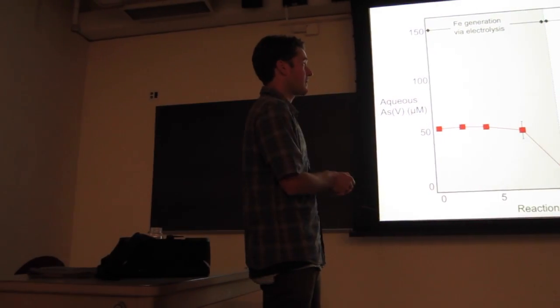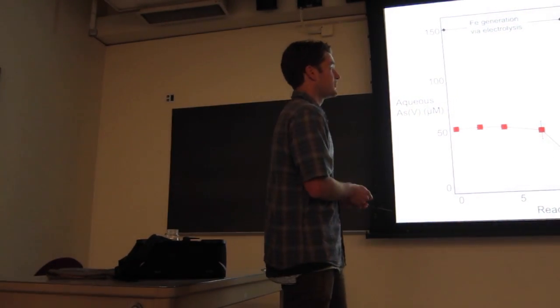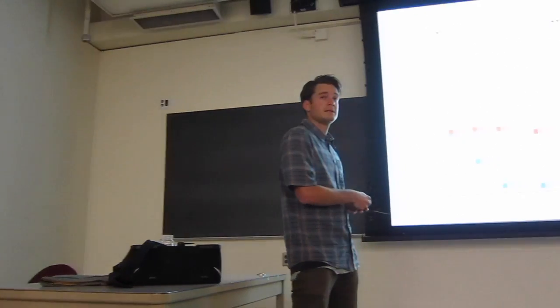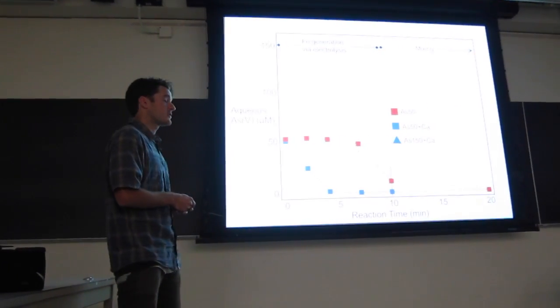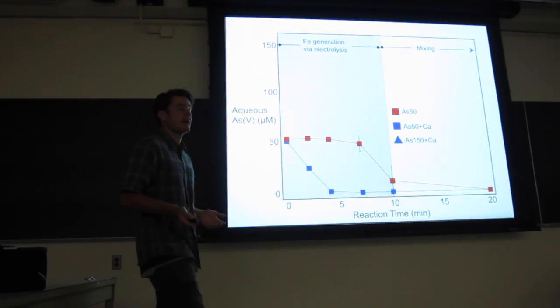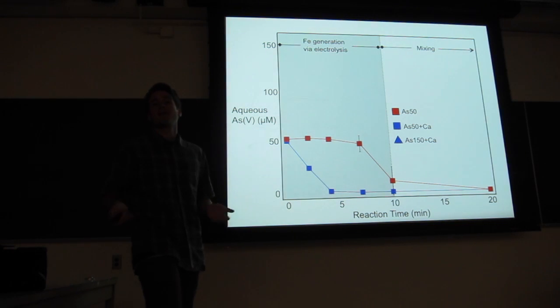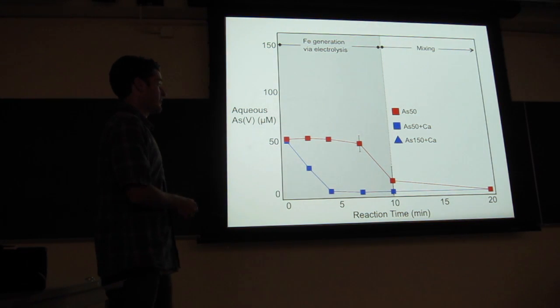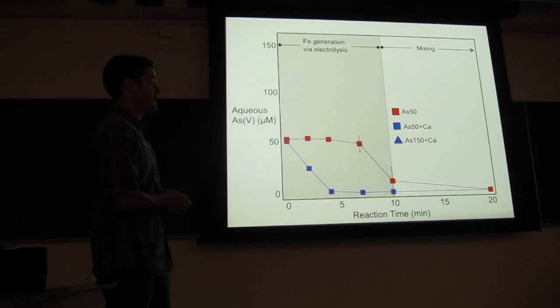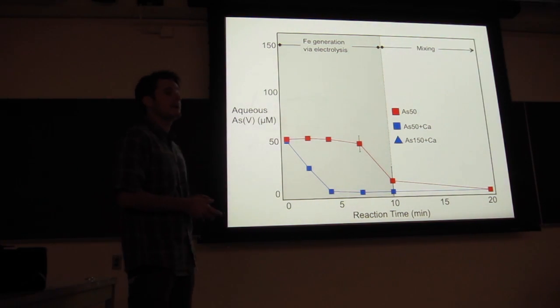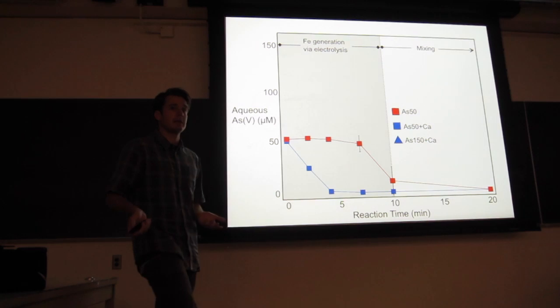So what this is telling us is that the majority of iron in this sample, this arsenic 50 sample, is generated in the presence of arsenic 5. When you add calcium at the same arsenic concentration, you have a rapid depletion here. And so about 4 minutes into the electrolysis, the electrolyte is essentially free of arsenic 5, and it looks like a background electrolyte, something like sodium chloride. So that means that the majority of iron generated in this sample, this AS50 plus calcium sample, is generated in an electrolyte that has no arsenic in it.